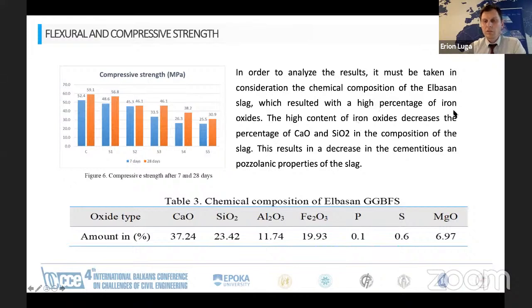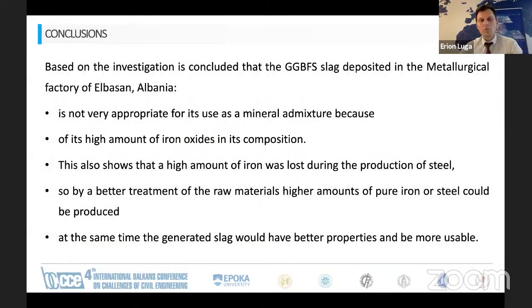The high content of iron oxide decreases the percentage of calcium oxide and silicon oxide, which are very important for the binding and pozzolanic properties of these mineral admixtures. This results in a decrease in the cementitious and pozzolanic properties of the slag. To come to the conclusions, based on the investigation, it was concluded that this ground-granulated blast furnace slag from the metallurgical factory of Elbasan, Albania, is not very appropriate for use as a mineral admixture because of its high amount of iron oxide.